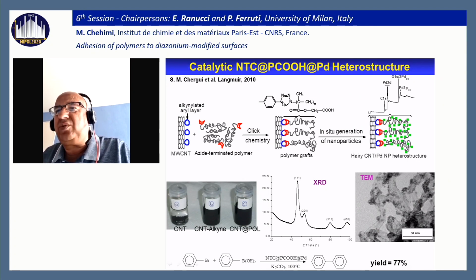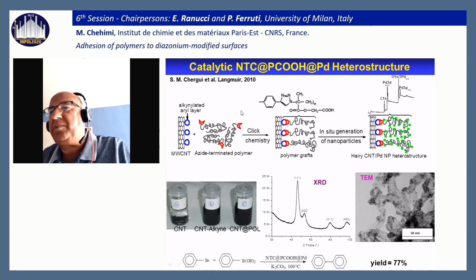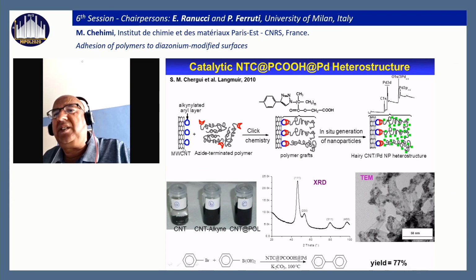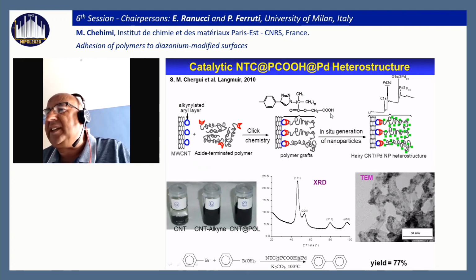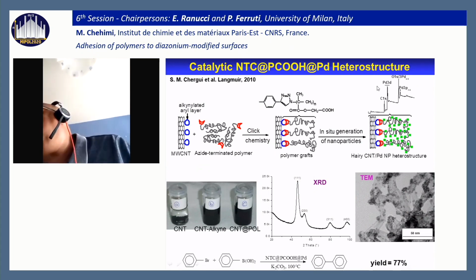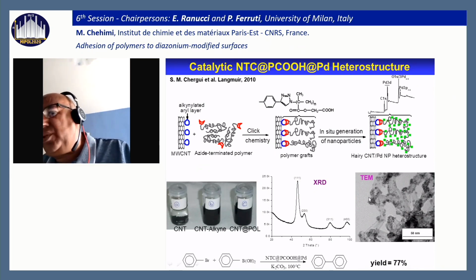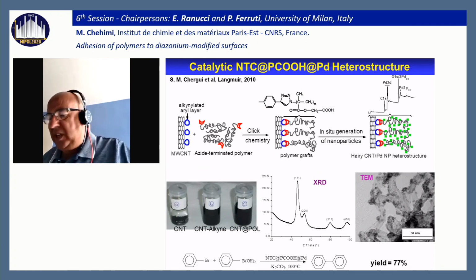I didn't plan to show this, but because we talked about click chemistry yesterday, we made alkyne-modified carbon nanotubes. We prepared by ATRP an azide-terminated polymer, which we clicked on the surface. It's from polyglycidyl methacrylate. We opened the epoxy here, and then we immobilized palladium salt, which we reduced in situ to make a nanocomposite with immobilized palladium nanoparticles for Suzuki CC coupling